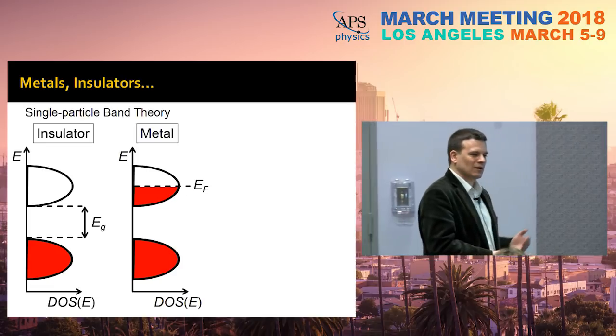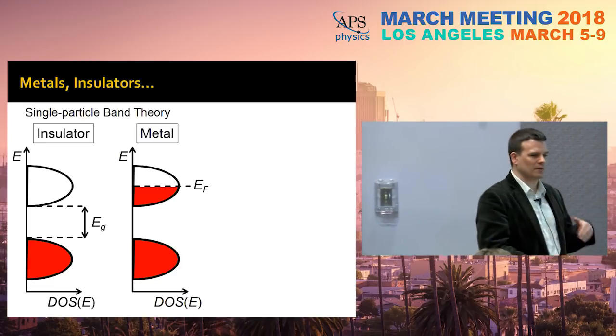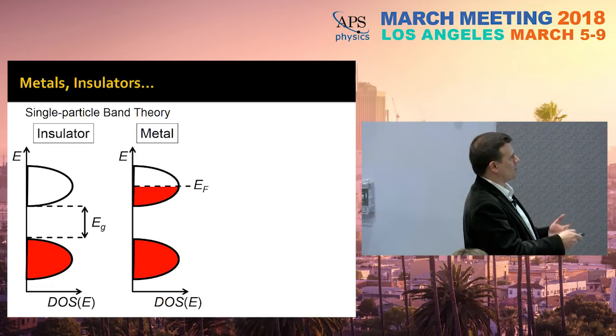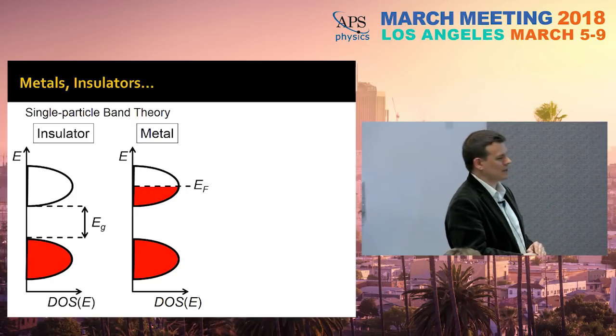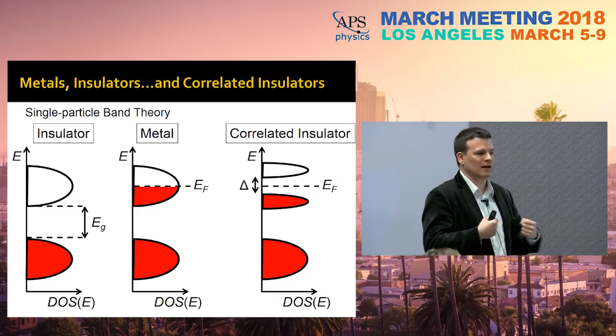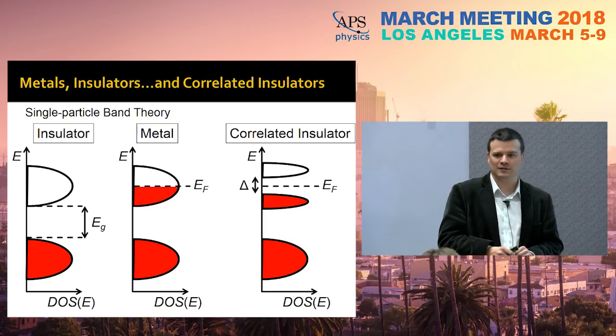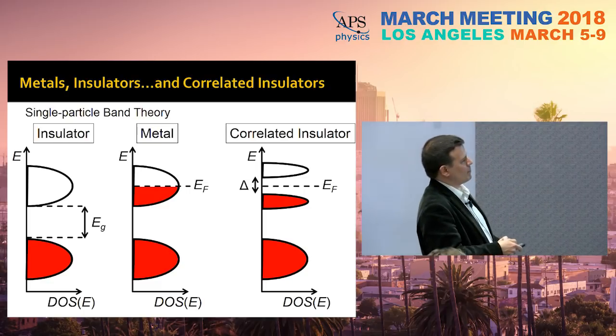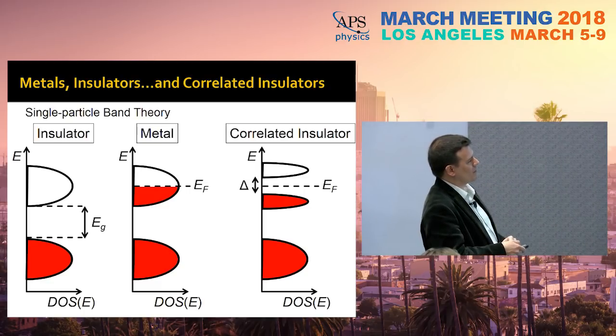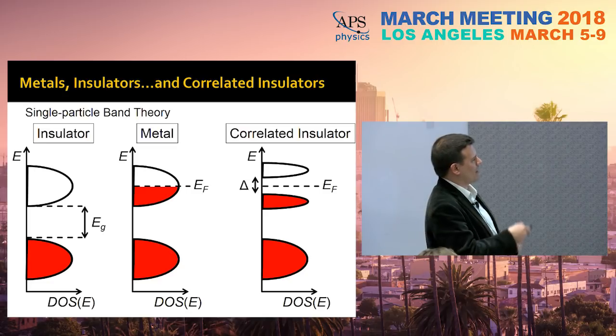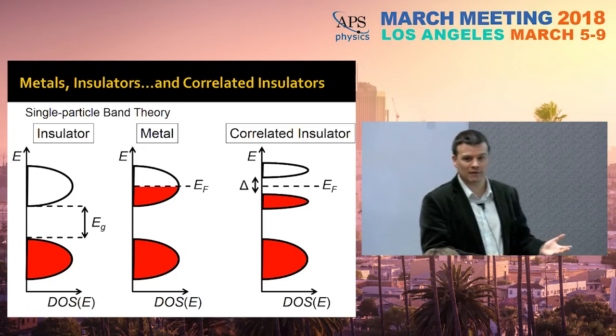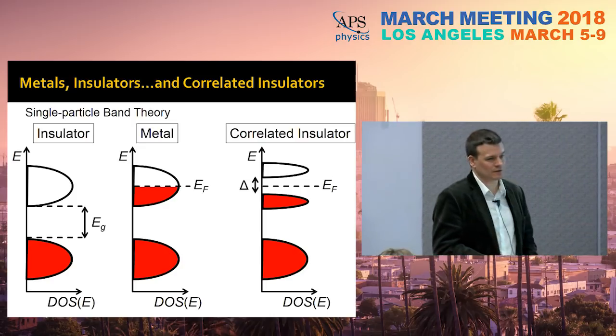Now, sometimes you have this situation where something that should be a metal, because you have just partly filled your band, actually becomes an insulator because of the strong interactions between these electrons in this material. So a gap opens, and you have a realization of something like a full band and a totally empty band. So you get an insulator, but this occurs in a situation in which you should have a metal, and this is a correlated insulator.